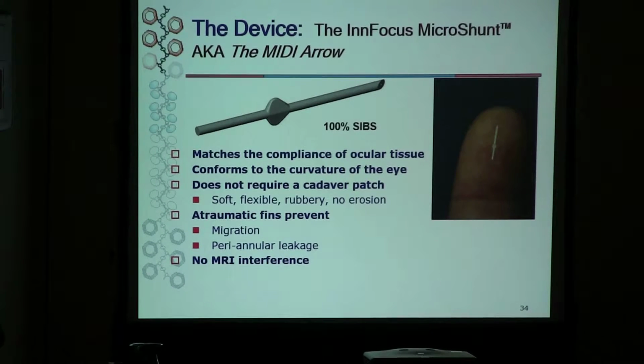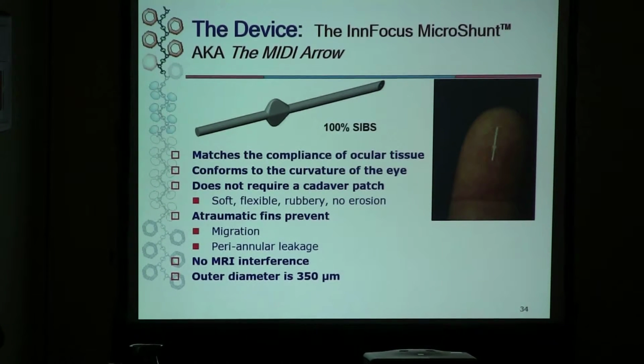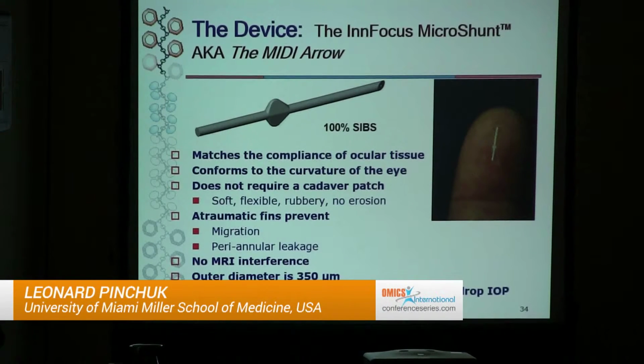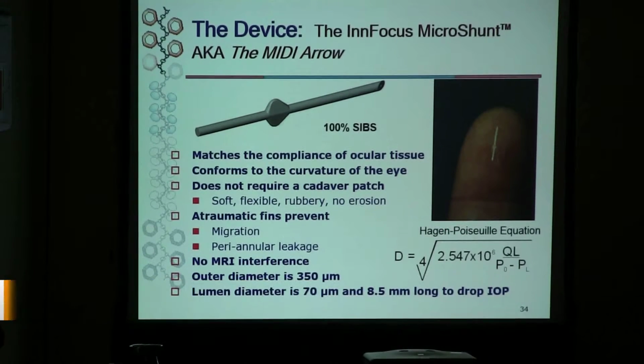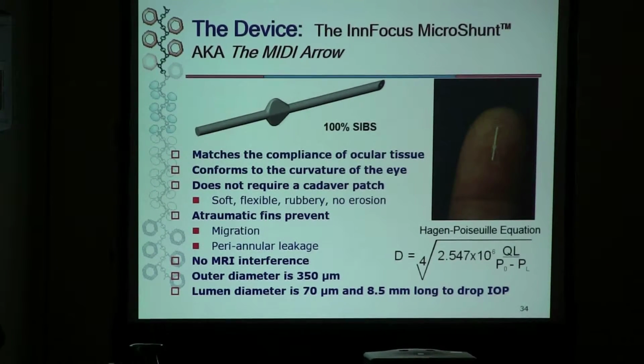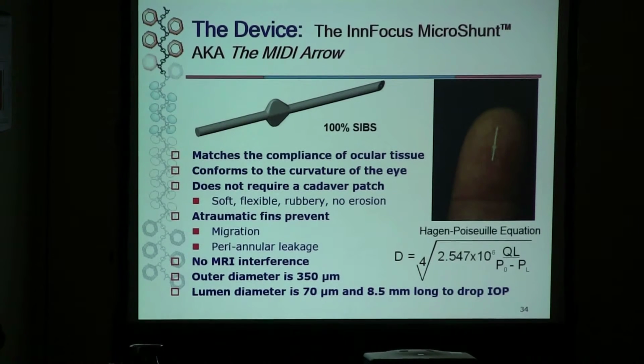There's no metal, so there's no MRI interference. The outer diameter is 350 microns. It actually can fit in the lumen of the Baerveldt tube. The lumen diameter is 70 microns, and we derived the lumen diameter from the Hagen-Poiseuille equation. However, we had to kind of tune it because we're very hydrophobic. We had to go larger than what Hagen-Poiseuille predicted.